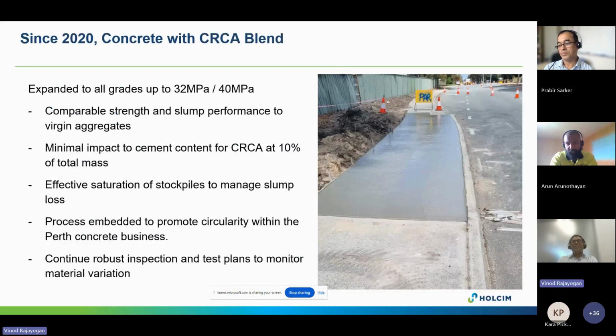And currently we have extended the recycled concrete aggregates up to 40 MPa in applications where a customer requires these. Obviously, the challenge has been that we have limited ourselves to 10% of the total mass or 30% coarse aggregate, and the problem always raised is, can we use more? That's where Curtin comes in, to understand whether higher replacement and other treatment methodologies can support us.